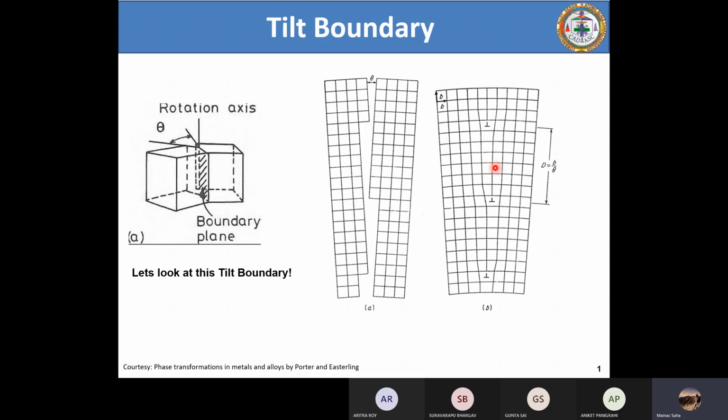Because the phase diagram is only going to consider your free energy in the bulk. It is not going to consider the free energy at the surface, or rather the grain boundary energy. So remember this always. You don't have to remember all the things, just remember that the phase diagram uses only the bulk free energy. It doesn't use the surface free energy. And if you thought that it could use the surface free energy, then the entire idea of the phase diagram would not be valid, because a phase diagram is always constructed under equilibrium cooling.